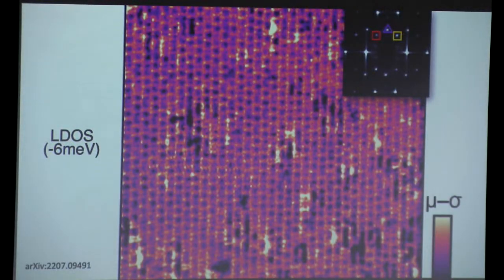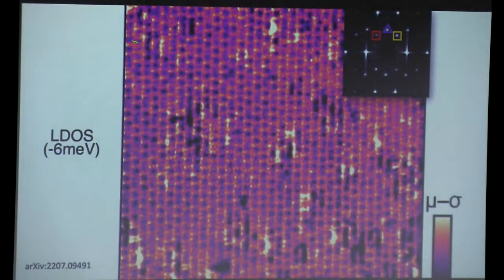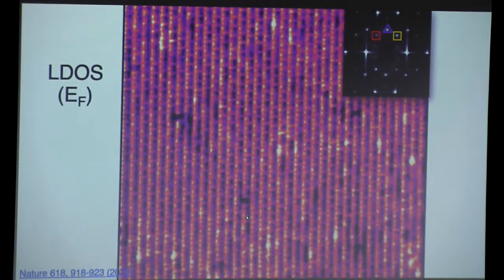This is the topography, and this is a dI/dV map at 6 millivolts, which looks very different from the topography. Here's the topography again, and here's the dI/dV map — you can see stripe-like features going in this direction. These correspond to this peak right here, because it has the right periodicity and direction. In addition, you can also see dots, which almost skip each other.